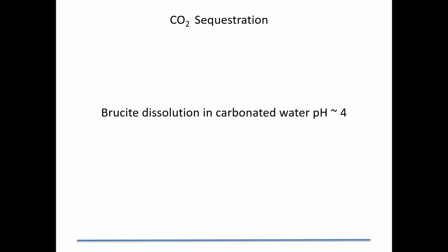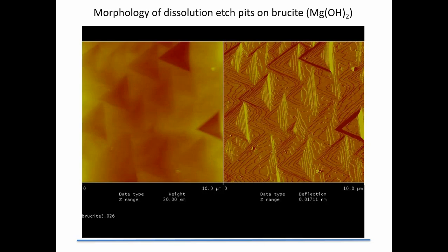Okay, how can we relate this to other things apart from toxic element sequestration? I took a brucite surface, and this is work with Jörn Hovelman, looking at carbonated water on brucite. Brucite is magnesium hydroxide, and it's a weathering product, or a product of olivine weathering. And here again, we've got the height image on the left and the deflection image on the right. That's brucite dissolving. Lovely triangular etch pits. Different all over the surface because we have different dissolution rates across the surface.